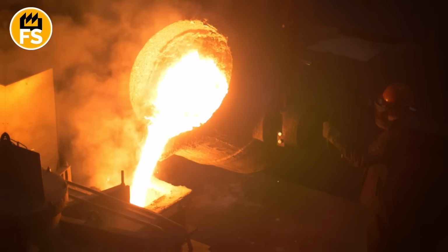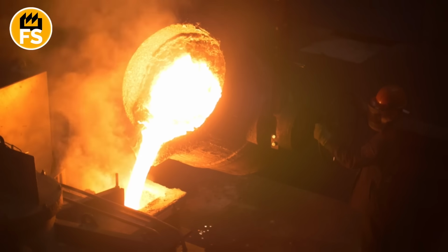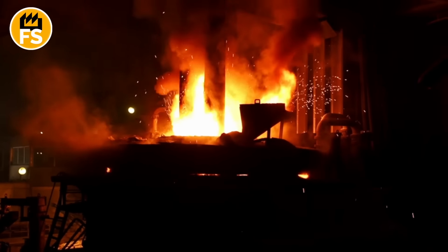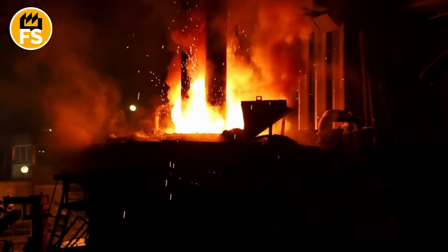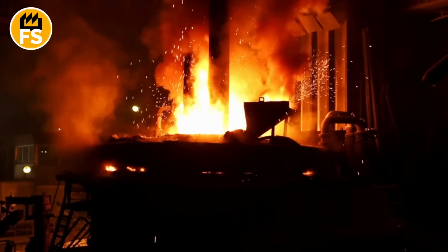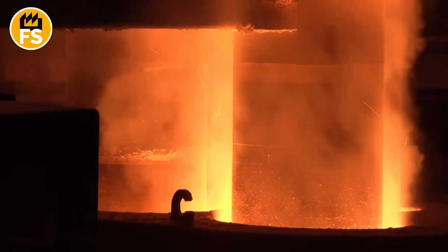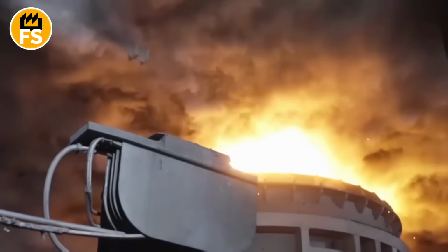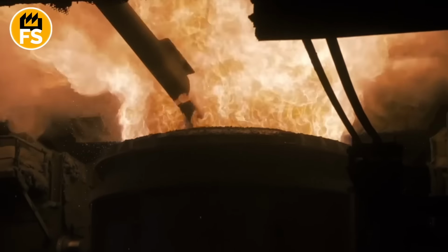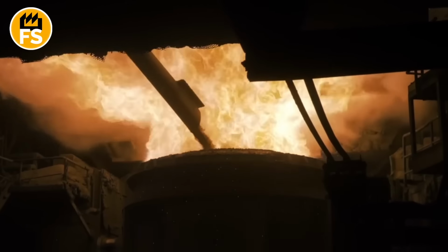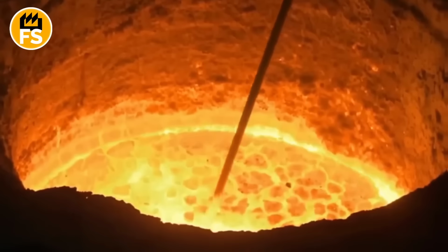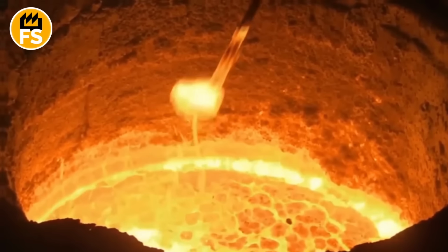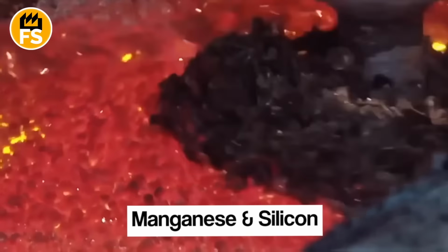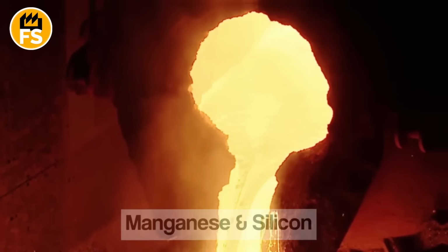They pour the molten iron from the blast furnace into this massive vessel, and then they blast pure oxygen into it at supersonic speeds, which ignites the carbon dissolved in the iron and creates these huge flames shooting 30 feet into the air. The entire process takes about 20 minutes, and during that time, they're constantly testing the composition and adding precise amounts of other elements like manganese and silicon to get exactly the right mix.